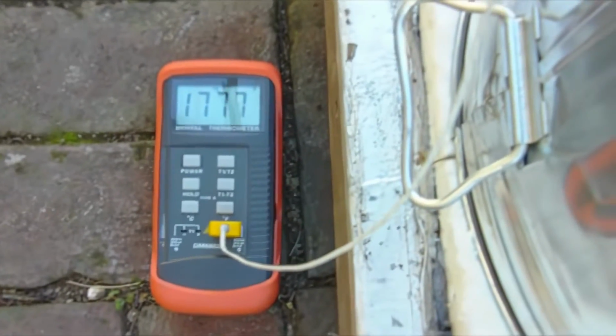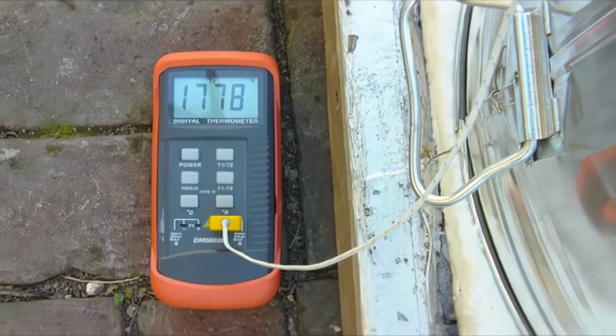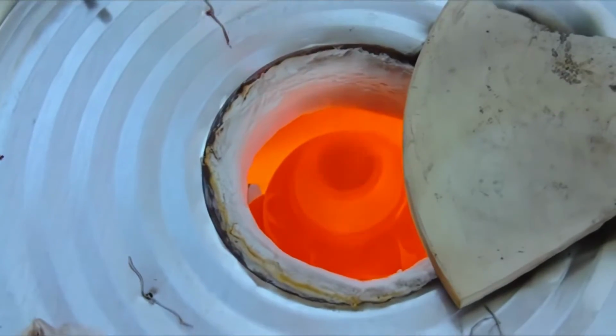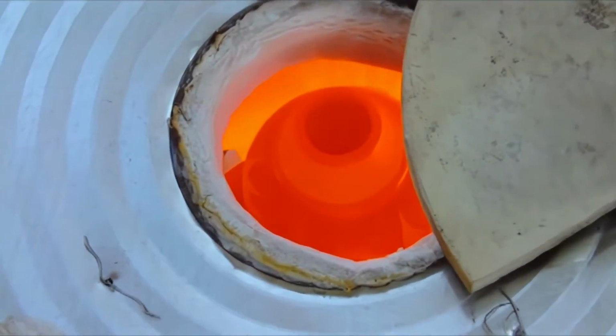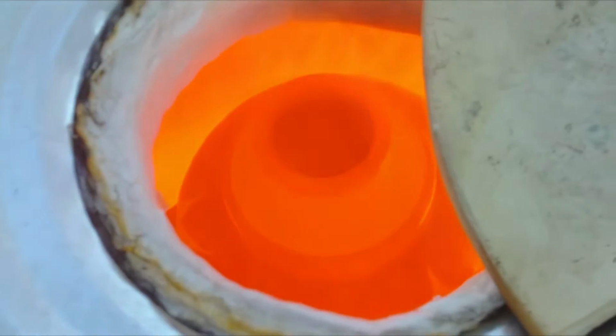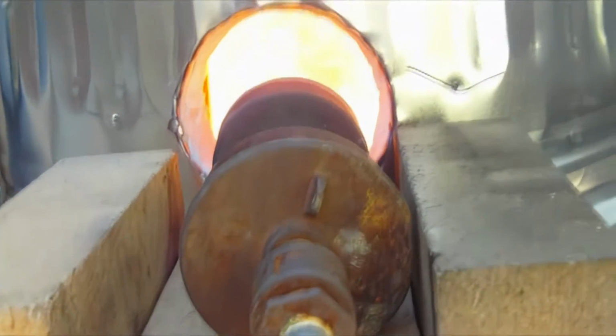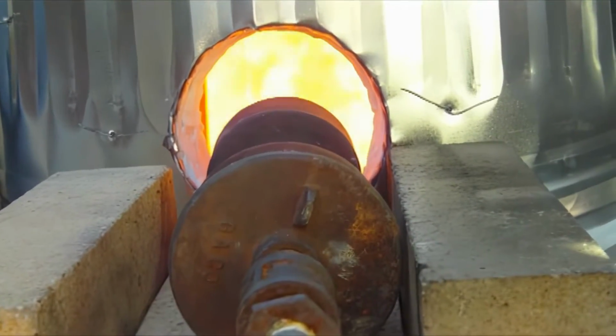You want to time your firing to about 30 minutes to get a good even glaze melt. Watch your pyrometer to see if it rises too fast or too slowly. You want to get to about 1800 degrees Fahrenheit in about 30 minutes, so adjust accordingly. Look into the kiln to see if your glazes look melted. If they do, and you're anywhere close to 1800 degrees, it's time to pull your pottery.